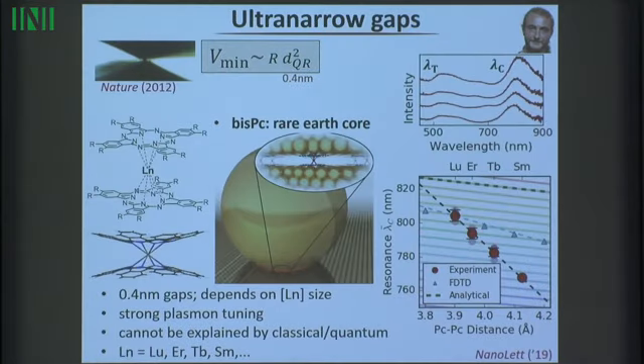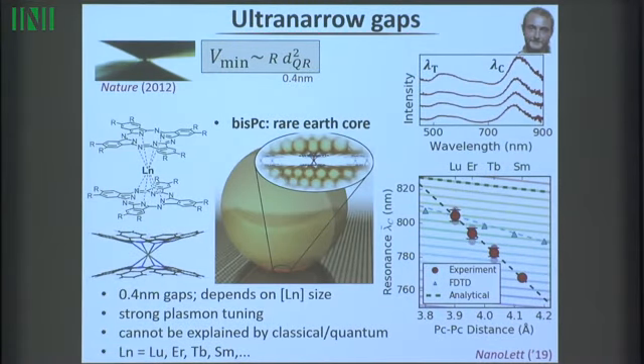And we've got well into this domain now, so this is a recent student in the group who's been making a molecule here which just nicely sits in these gaps, and this molecule is 0.4 nanometers. So it's at that quantum mechanical tunneling distance there. Again, we're basically measuring the color of it here. It scatters light. It's a very simple measurement. You could actually look down a microscope and see this. It's not a subtle effect. We can see the color here, and we can change this atom in the middle here. When we change the atom, we slightly change the size. That's it. And we look at the color changing, and it fits no theory in any fixed up way. So we're sort of completely beyond what people are capable of doing.